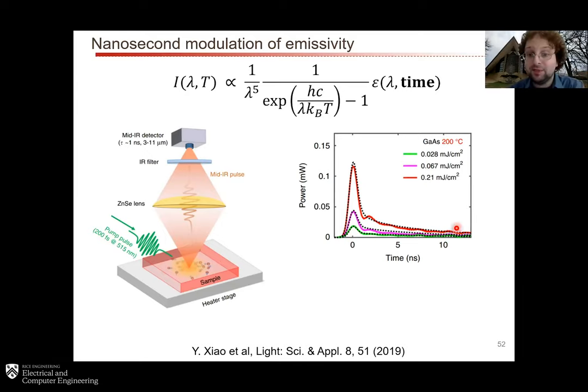And you can see the power versus time for different pulse energies and a particular temperature to which you're heating the gallium arsenide wafer. And you can see this nanosecond pulse and then this decay. So essentially what's happening here is that at first the gallium arsenide is undoped, and therefore the emissivity is very low, and the amount of thermally emitted power is essentially zero. You hit this thing with a pump pulse, you promote a bunch of carriers from the valence band to the conduction band, your emissivity changes a lot, and you have this peak in thermal emission. And then as the free carriers recombine after a few nanoseconds, you have a decrease in thermal emission and then eventually a recovery. In this case, also hidden in this measurement is a much narrower hot carrier pulse that's just a few picoseconds wide, that is essentially convolved with everything else because our detector only has a time scale of about 1 nanosecond.